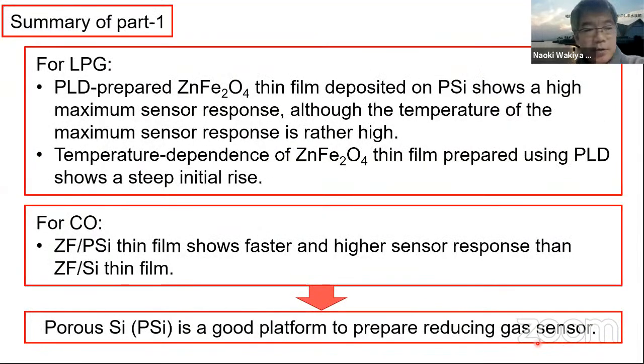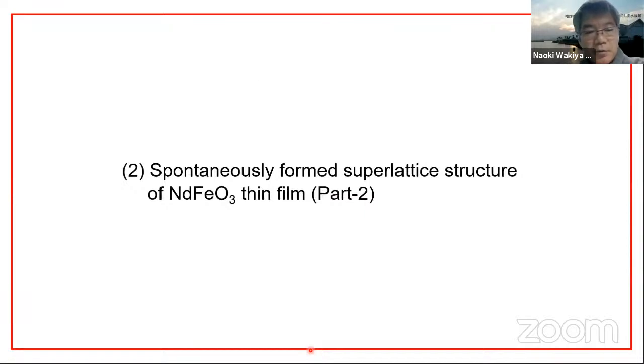This is a summary of part one. The PLD prepared zinc ferrite thin film on porous silicon shows a high maximum sensor response. Although the temperature of the maximum is high, the temperature dependence of the zinc ferrite thin film prepared using PLD shows a steep initial rise. And for the CO gas, the sensor response of zinc ferrite deposited on porous silicon is faster and higher than that of the film on silicon substrate. So this means that porous silicon is a good platform to prepare reducing gas sensors. This is part one, and this is part two, the new concept.